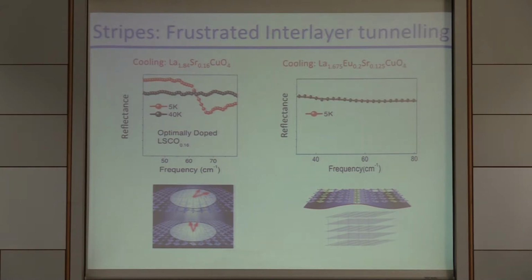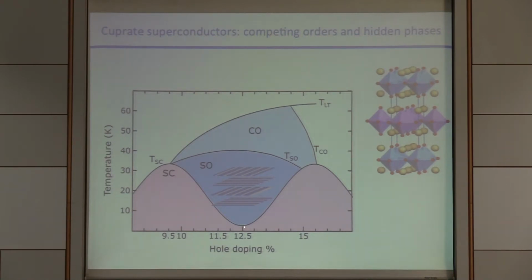Another way to say this is that the c-axis electrodynamics of a layered cuprate is basically LC electrodynamics, because you have inductive tunneling and capacitive planes. So this system has a resonance and it rings like a bell if you perturb it, and hence you see this plasma resonance that tells you it is very long-lived, as you can see from the fact that this edge has a relatively small width compared to the frequency, and the position of this edge tells you about the superconducting order.